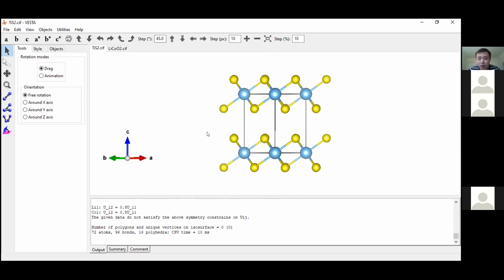If you still remember our previous lecture, I mentioned HCP stacking is very rare in the lithium cathode, because in HCP, you will have the face sharing between these cations, and if you have cation in this layer, these two cations will face share and have a lot of repulsion. Only when you extract all the cations in this layer, you're creating the vacancies.